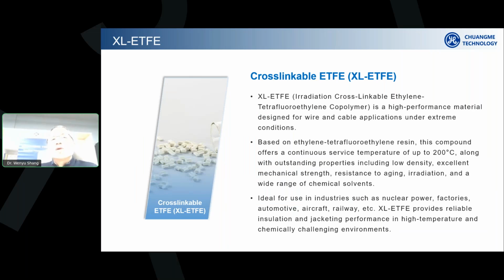So after all these procedures, the cable has a cross-linked ETFE as the insulation protective layer, and that can help the cable sustain a long-term continuous service temperature of 200 degrees C. So that is how the whole procedure works, and that is the global industrial standard used for aerospace cable that needs to sustain 200 degrees C temperature resistance.